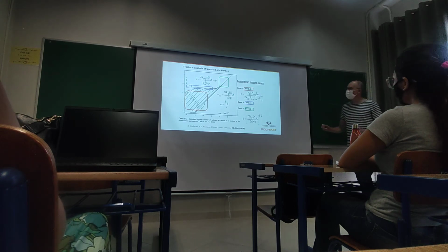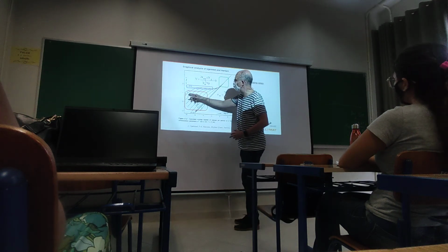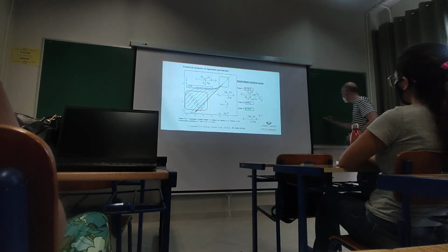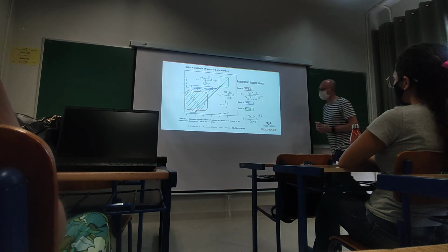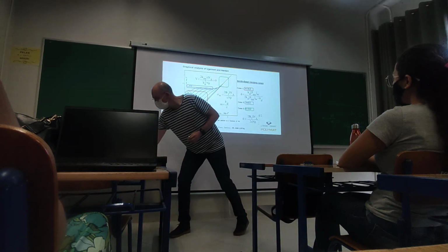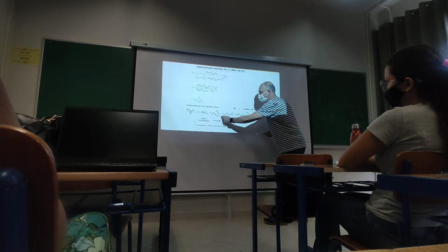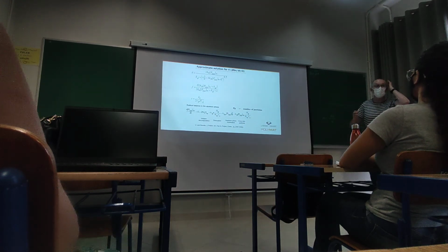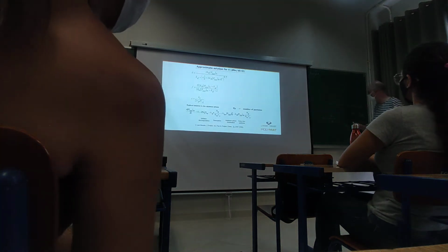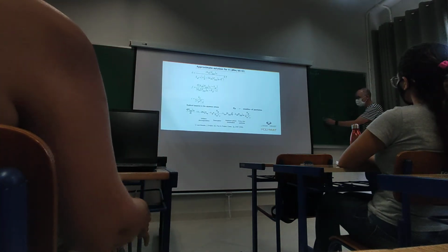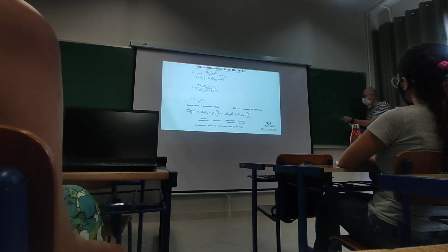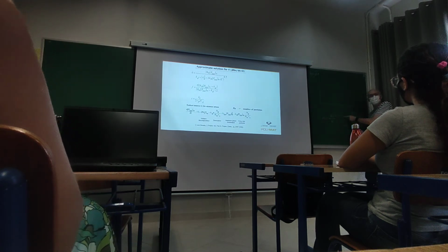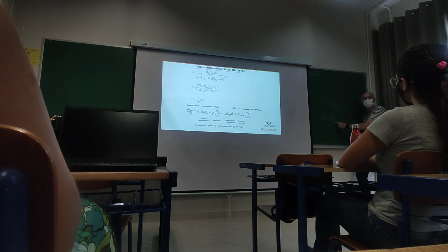The second parameter that they use in the graph is N. N is KD divided by C. And this is obtained by dividing this by C and P also, okay? With adjusting the Avogadro's number and the volume of the particles. But this N value is a ratio between the rate of exit with respect to the rate of termination inside of the polymer particles.